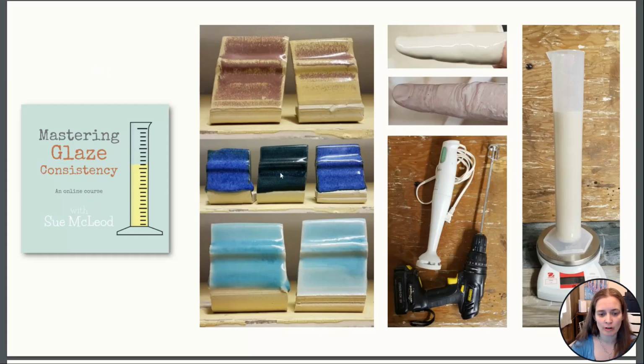Some glazes are very drastic. This is our sapphire blue glaze. This has minimal water content, so a high specific gravity. And then this is where I added more water to lower the specific gravity. All of a sudden, the glaze is too thin to give a very good application layer.